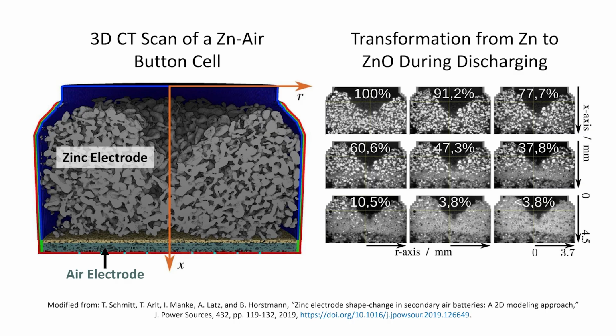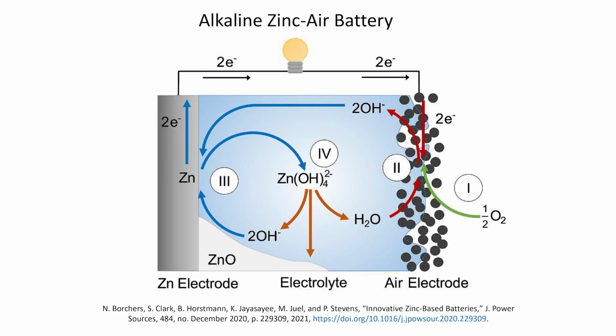Which is many, many zinc particles that are all interconnected and form a thick porous structure where those hydroxide ions will then react with zinc to form zincate and eventually precipitate out as zinc oxide. So the zinc part is also a bit porous, like the air part is porous, you just said. So the zinc part is also a porous structure? Exactly. And this is the name of the game in batteries, creating good interfaces. Because that's where the reactions are going to take place.